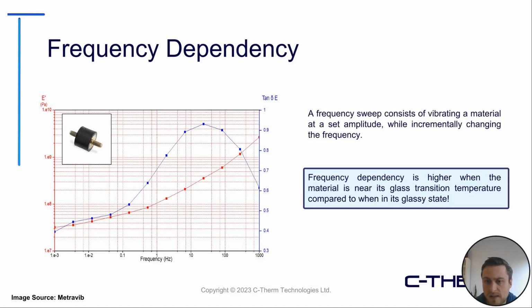Frequency dependency is higher when the material is near its glass transition temperature compared to its glassy state, where it'd be more consistent and there'd be less of a frequency effect. This is because the material properties change drastically near the glass transition temperature, so any change in strain or frequency can have an adverse effect on your material properties.